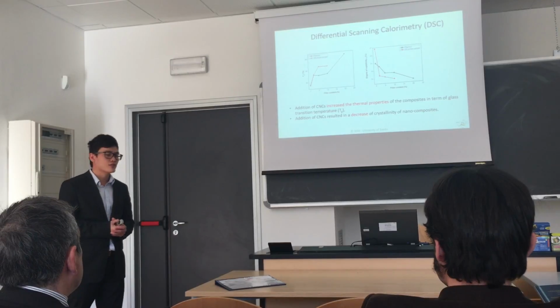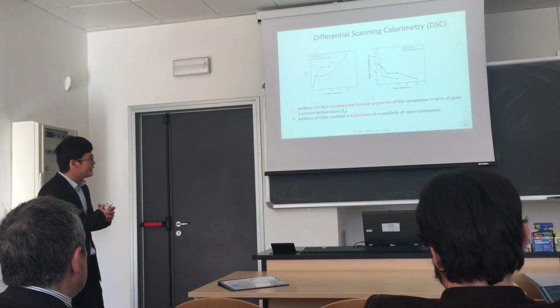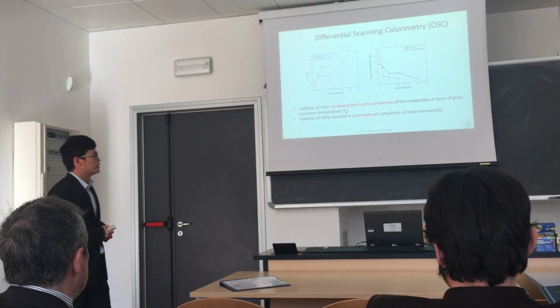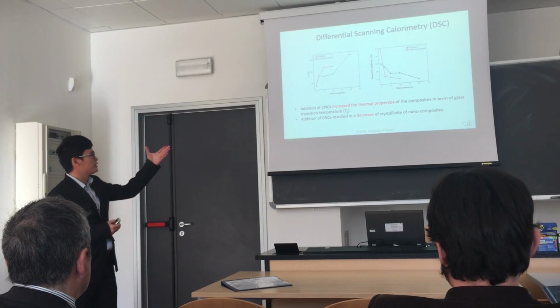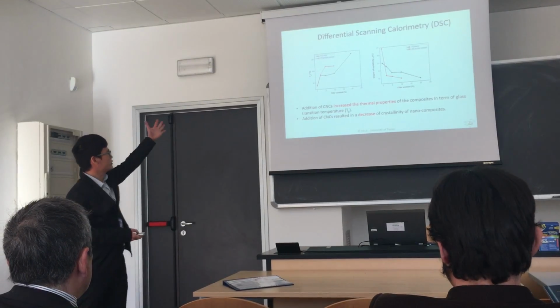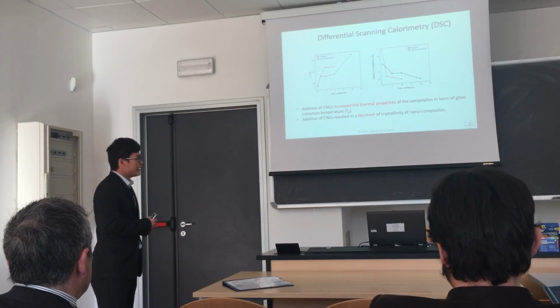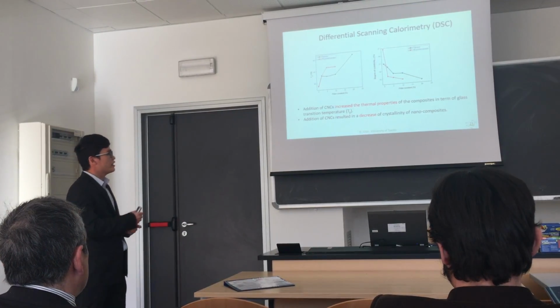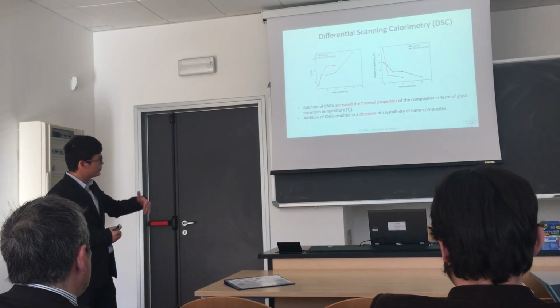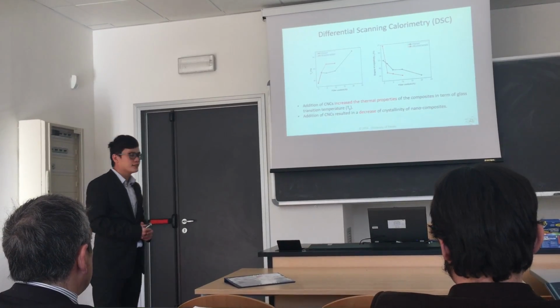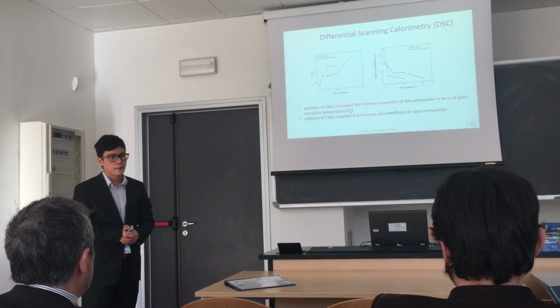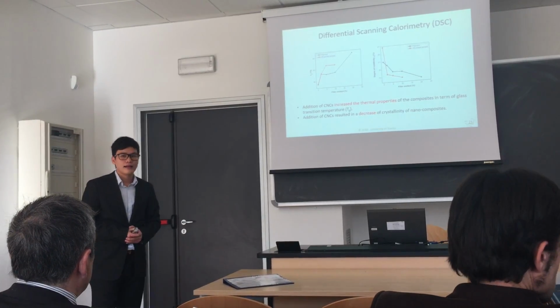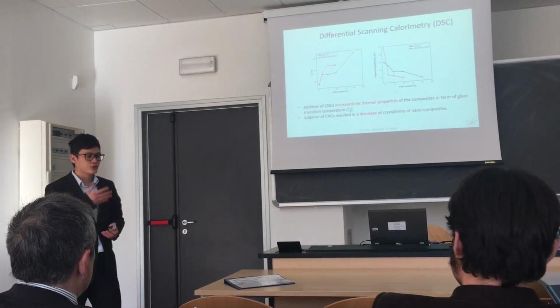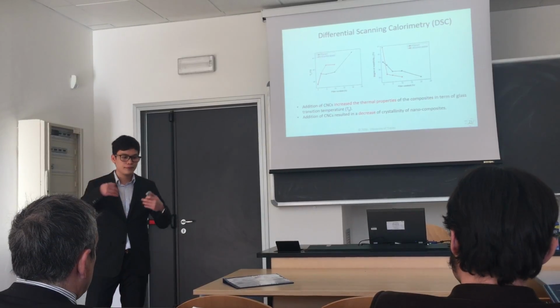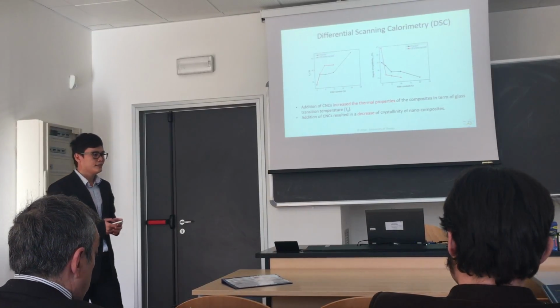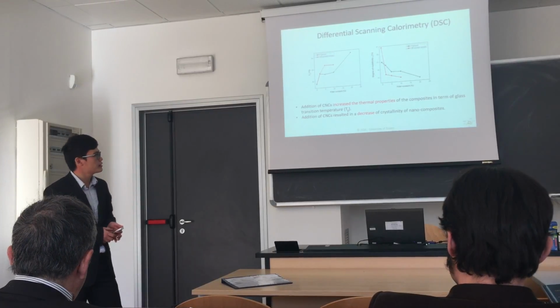With the addition of the nanocellulose, there was an increase in the thermal property in terms of the glass transition temperature, which we can see in the left figures. Another striking feature is that the introduction of the nanocellulose tends to decrease the degree of crystallinity inside the nanocomposites. This behavior can be explained by the nanocellulose hindering the polymer mobility, which leads to a decrease of the nanocomposite crystallinity